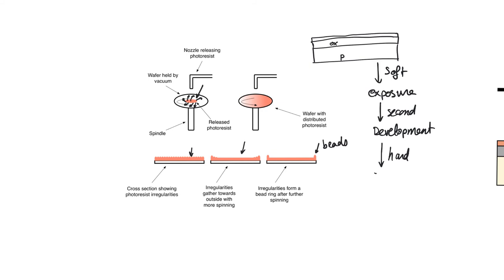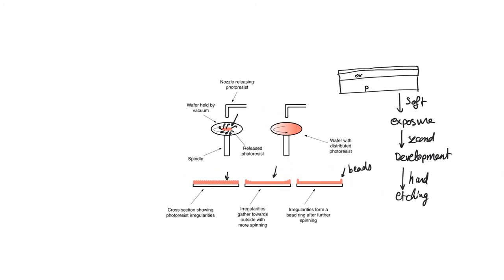The hard bake must be done before etching. Etching is the process by which we open features through the oxide: after development exposes part of the wafer, an etchant — in wet etching, usually a liquid — eats through the oxide below. At this stage we need the photoresist to adhere extremely well to the oxide where it has not been developed, to protect that oxide. We couldn't have done the hard bake from the beginning because it would have severely complicated exposure and development.